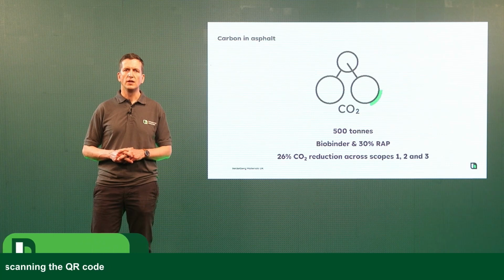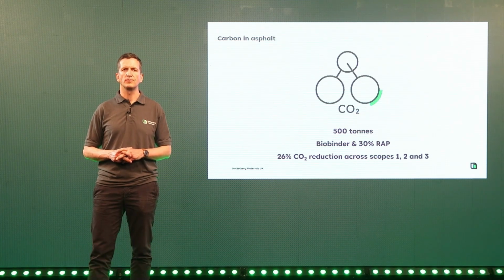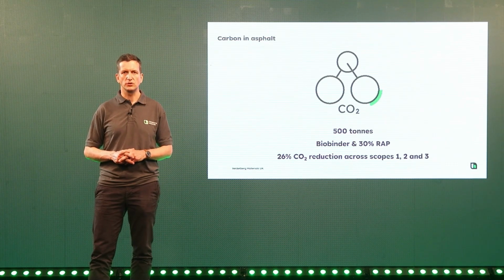The use of our ERA 140 warm mix asphalt will contribute to reducing our scope 1 emissions by around 3%, while the biobinder will reduce scope 3 emissions by around 23%. Each trial will include around 500 tonnes of carbon lock asphalt, with the use of biogenic material absorbing and storing CO2 throughout its life, even when it is recycled, reducing the carbon emissions associated with asphalt by around 26% across scope 1, 2 and 3 in total.